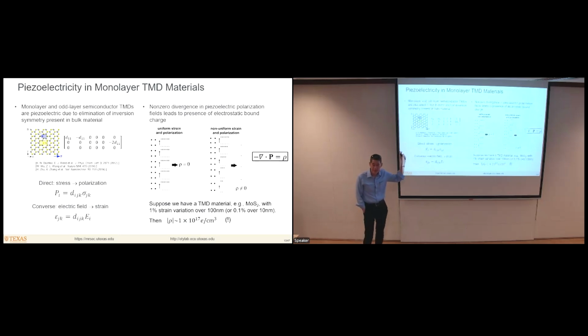So piezoelectricity, which as many of you probably know, is essentially a coupling between stress or strain and dielectric polarization in a material. It's actually a very interesting behavior in these transition metal dichalcogenides, because if you have bulk material, right, where you have these layers stacked on top of each other, then successive layers are stacked on top of each other with opposing orientations. So that structure is centrosymmetric. And in order to have non-zero piezoelectricity, the material has to be non-centrosymmetric because it's governed by a third order tensor as shown here. Okay, so bulk TMD materials are not piezoelectric.